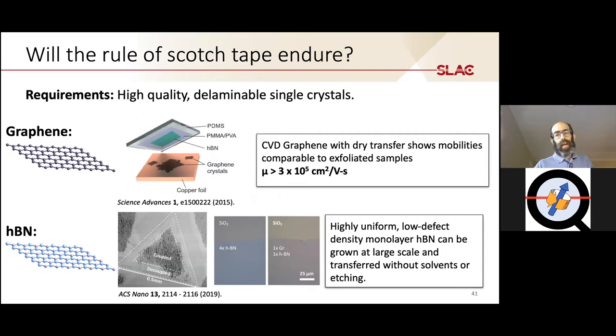But I'd like to pursue another direction, which is based not on exfoliated materials from bulk crystals, but rather on large area grown monolayers. It turns out that CVD graphene quietly has already become as good, as far as we can tell, as exfoliated materials. It's just that you need to stack it with other stuff. Boron nitride is less clear that it's there, but the monolayers are getting quite good.